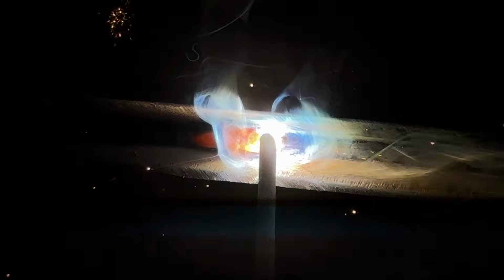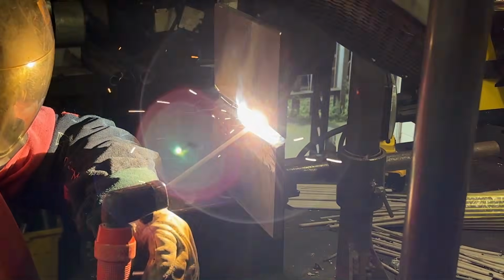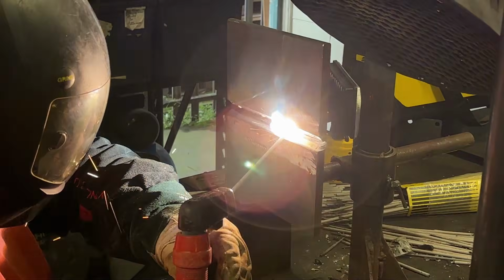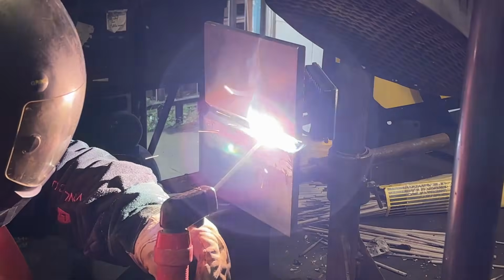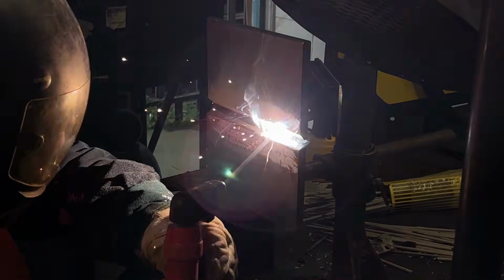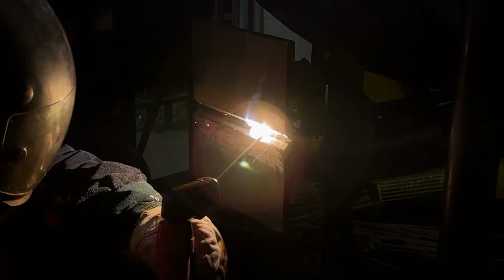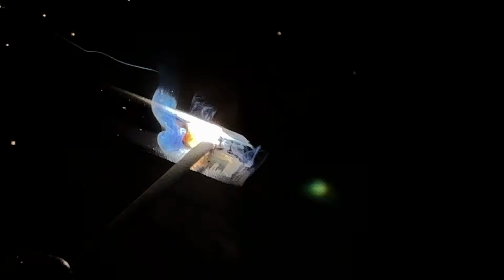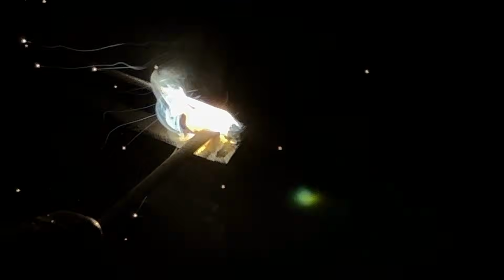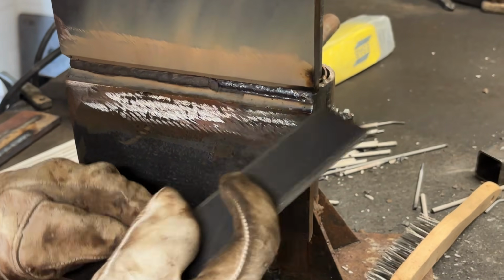Too many amps or lingering in one spot can overheat that root and push additional metal through to the back side, which can distort or disturb the root bead we've already established. But with that in mind, we still have to remember to fully fuse into that run to burn out any areas of lack of fusion. As you can see, we're putting a slight weave on the rod to ensure it fully covers that first run. Once that pass is complete, we get our chipper out, knock that slag off and check that the bead is tied in properly and is covering that previous run nicely.